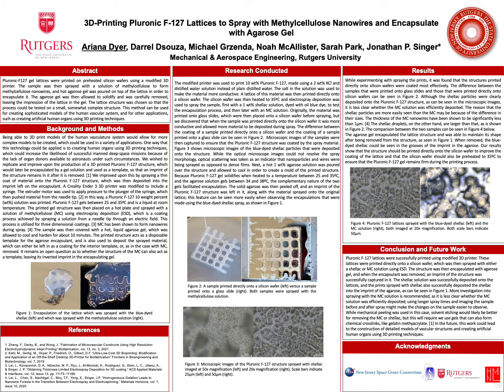After the printing process was complete, microscopic images were taken to ensure that the sprayed material had been deposited onto the Pluronic F127 lattice. Although the shellac particles were clearly deposited onto the lattice, it is less clear whether the methylcellulose spray was deposited. This could be because of the differences in the sizes of the particles. The methylcellulose nanowires' thicknesses have been shown to be less than 1 micrometer, while the shellac droplets are larger, as can be seen in Figure 3 on the poster.